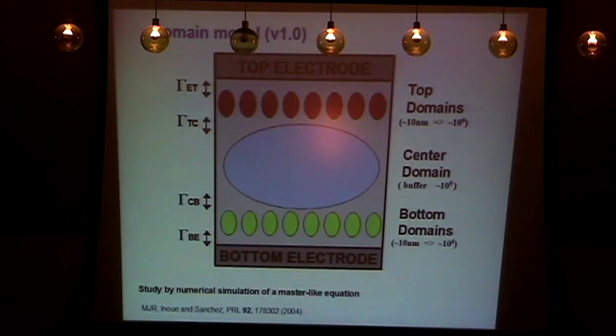So the first model that we introduced in collaboration with Isao Inoue and Maria Jose Sanchez several years ago was just out of intuition because very, very little was known at that time. So the model we proposed was called the domain model, in which we imagined that in between the electrodes there was a big insulating matrix which remained inert, and then you have domains near each one of the two electrodes, and then a large domain that acts like a buffer that separates the two interfaces in the middle.